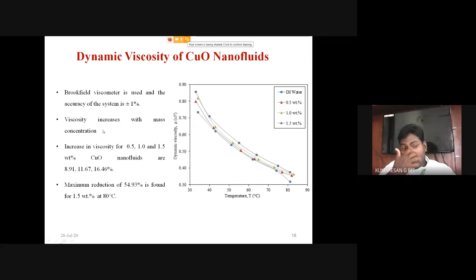That viscosity increases with increasing the mass concentration, because if you are adding that high volume or mass concentration of nanoparticles in the base fluid, its density increases, then automatically viscosity increases. Then the increase in viscosity for 0.5, 1.0 and 1.5% of CuO nanofluids are 8.91, 11.67 and 16.46% respectively. Then a maximum reduction of 54% is found for 1.5% at 80 degrees Celsius. At this point, you see the viscosity of the 1.5% nanofluid compared with the DI water, which is operating at 80 degrees Celsius. It shows that the viscosity of the working fluid drastically reduces by increasing the temperature value.